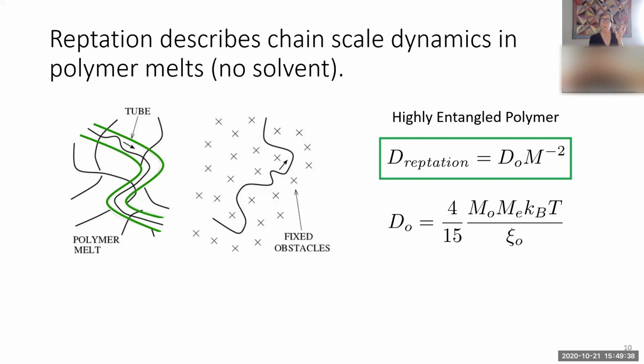So polymer center of mass motion goes by a mechanism of reptation, which is based on a tube model. And I'll just remind you that a polymer is contained in a tube, and the lateral dimensions of the tube diameter are defined by entanglements. And so a highly entangled material, with a small entanglement degree of polymerization, will have a much denser array of entanglements, and that narrows the tube and makes diffusion more difficult.